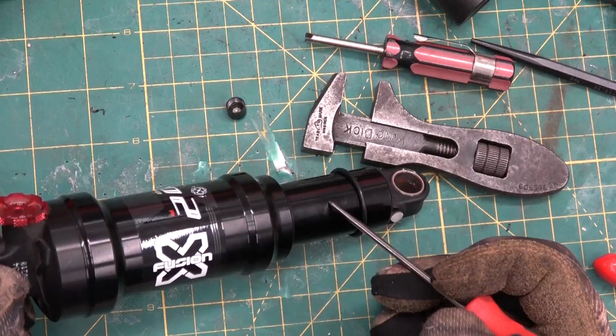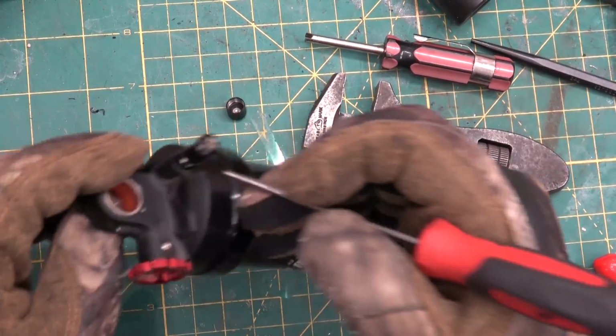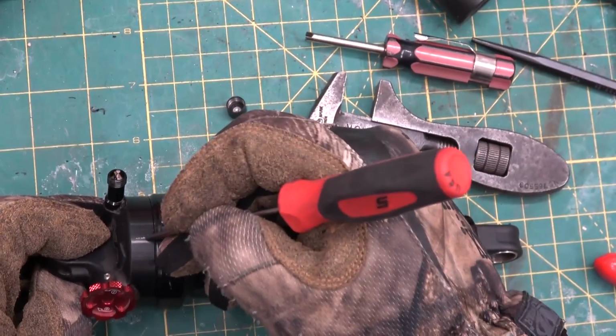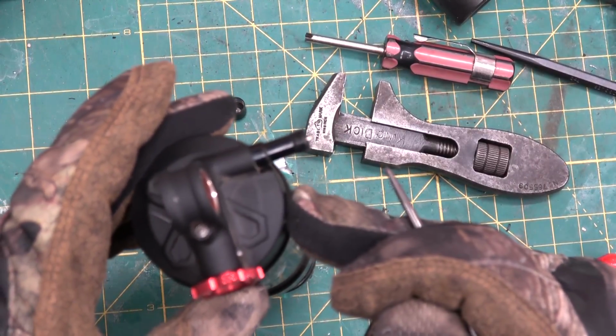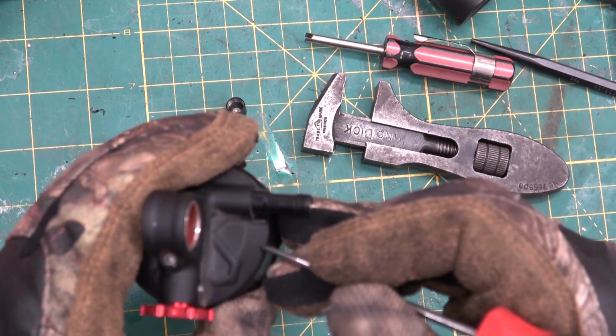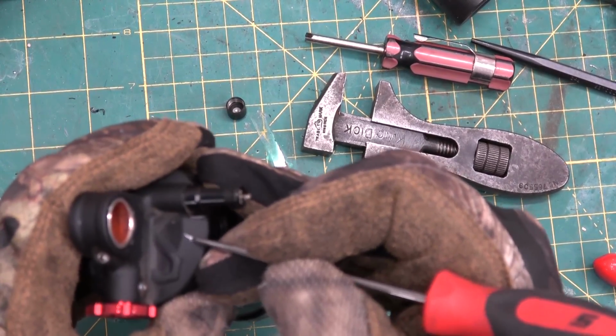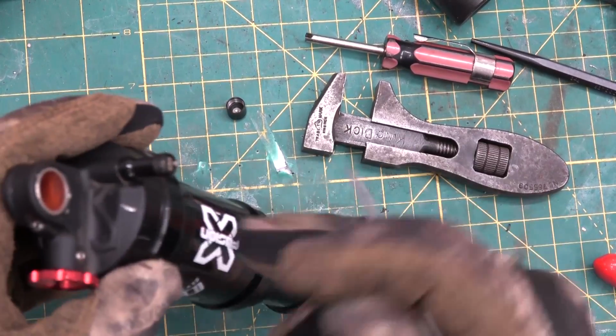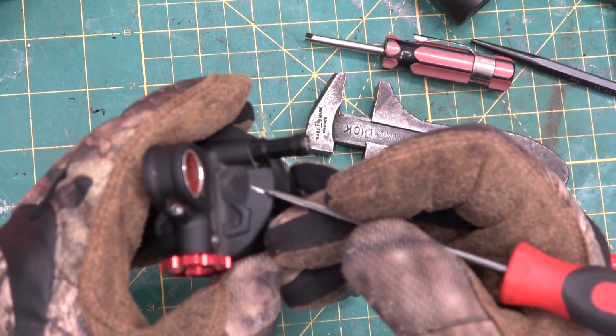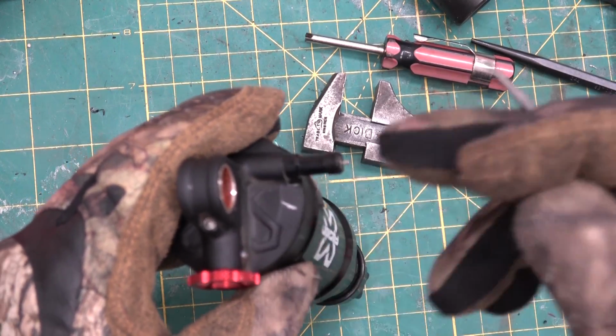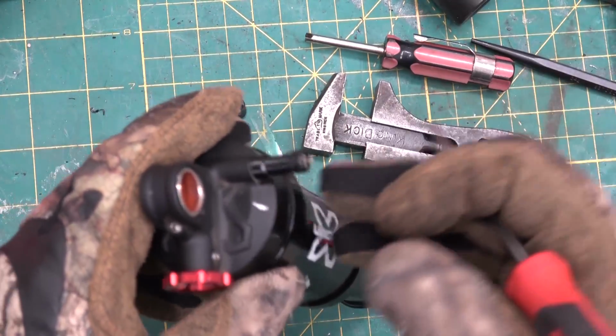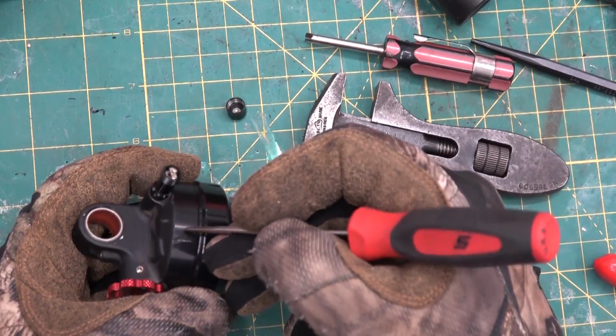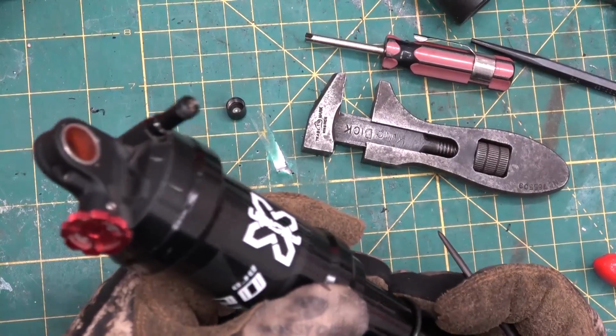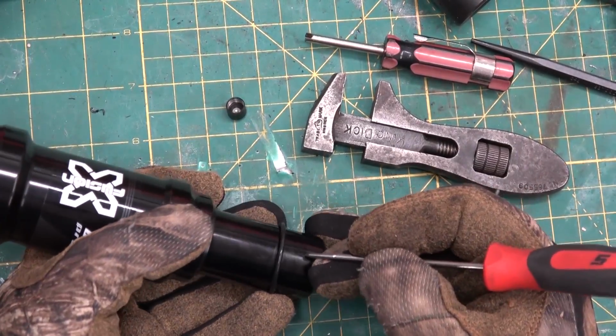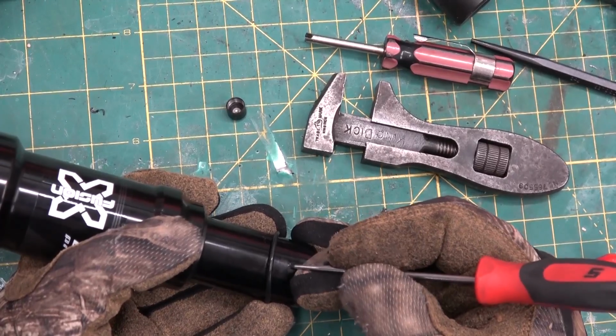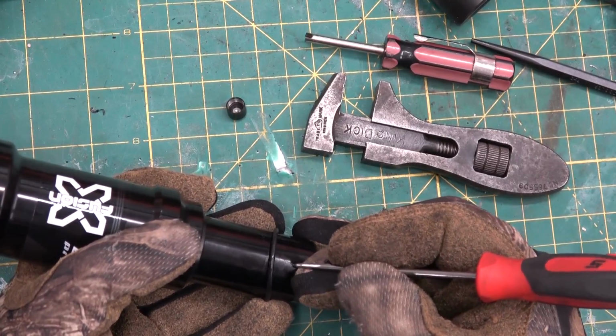So what we're looking at here, and just let me prove it to you. If we look at that one, that comes off pretty easy. On the back side here, it's a totally different process. That's been painted with a plastic powder and then baked on, powder coating, they call that. And that's also done with the aid of electricity, very high voltage, that causes the powder to stick to the part, and then they cook it in an oven and it melts all together. But this section here is anodized. Now look at the difference. I scratched that pretty good. Now I take a scratch of this, and it's quite a bit harder. I really have to push on that to break through that oxide layer.